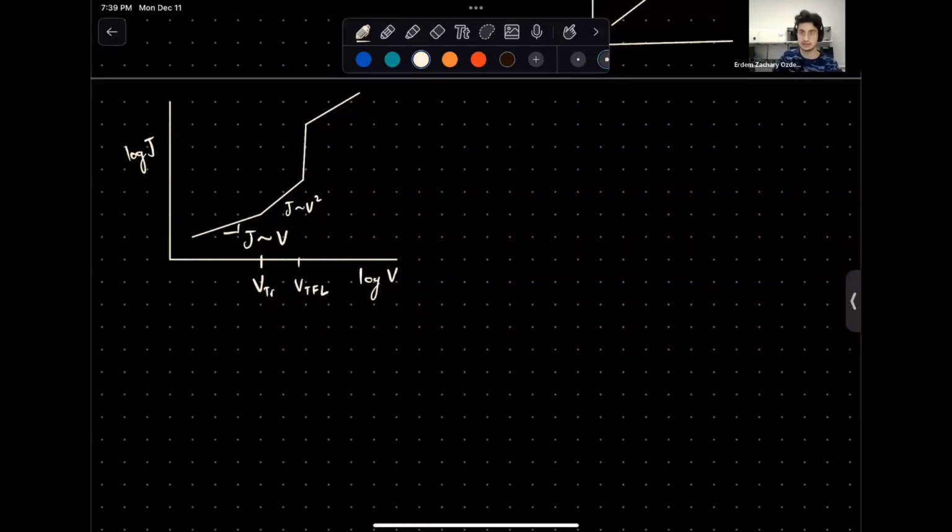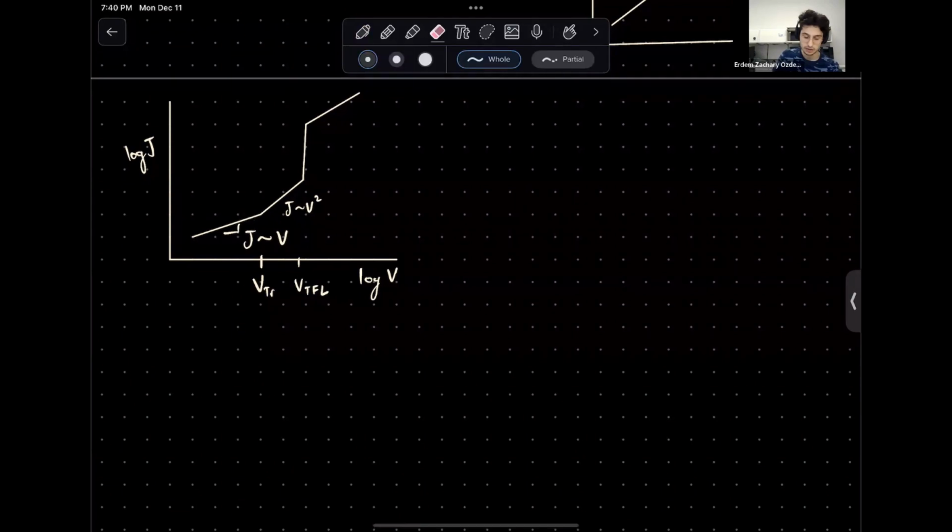Basically, we have those traps, let's say, again, nitrogen vacancies in aluminum nitride. We're sending electrons through this material, and electrons are getting trapped in those sites. Now that there are electrons there, further electrons will pass over these traps. So up until here, we have purely ohmic conduction. Here's where we start filling those traps.